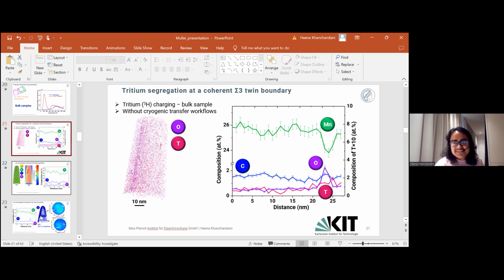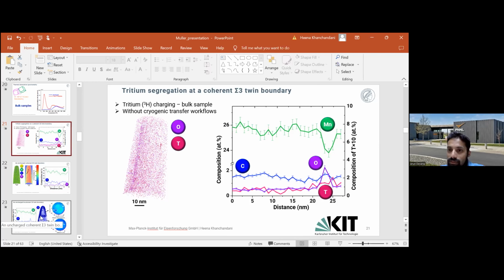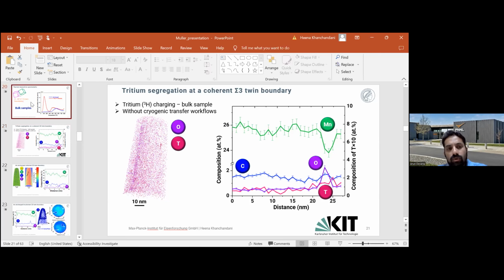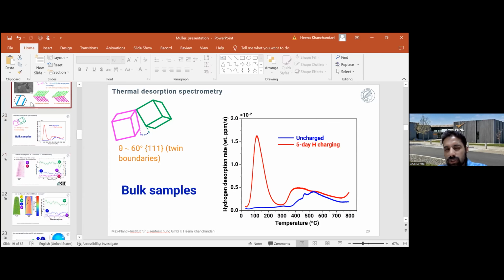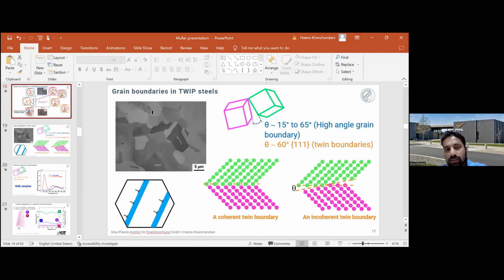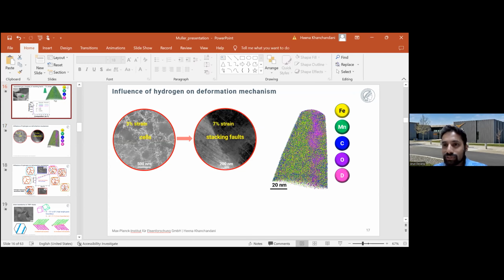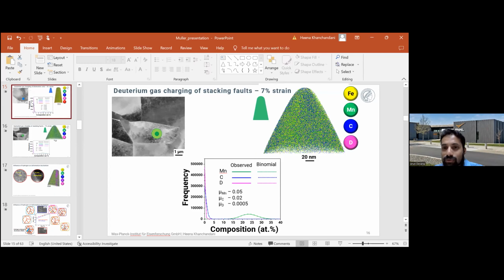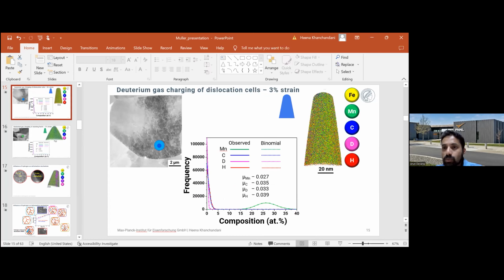Yeah, we have some more time, so I can ask one more question. So in your study where you didn't see the dislocations having segregation, how quickly are you plunged? Like how quickly is the sample frozen after hydrogen charging? And can it be because the lattice trapped hydrogen is also there and everything is kind of high segregation everywhere and you're not able to distinguish what is deeply trapped at dislocations versus in the matrix? Well,